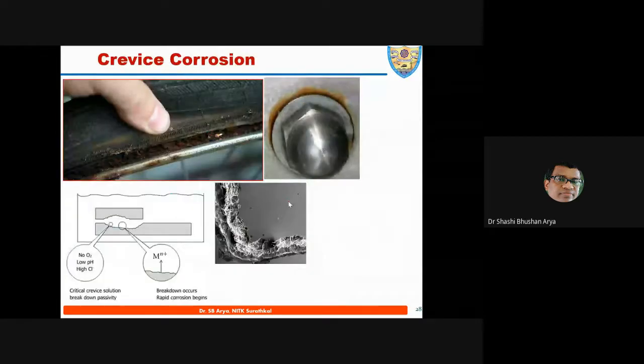Okay, some crevice corrosion I told you about: oxygen, the crevice rim, oxygen is there. Inside, you see the rim is corroding. Outside, oxygen is in excess, so it will provide some protection of passivity. But here there is no film formation, hydroxide or oxide. That's why the film is going to break. More crevice corrosion: if you do the punching, the fastener, washer and all, is the biggest problem. So these are crevice corrosion.